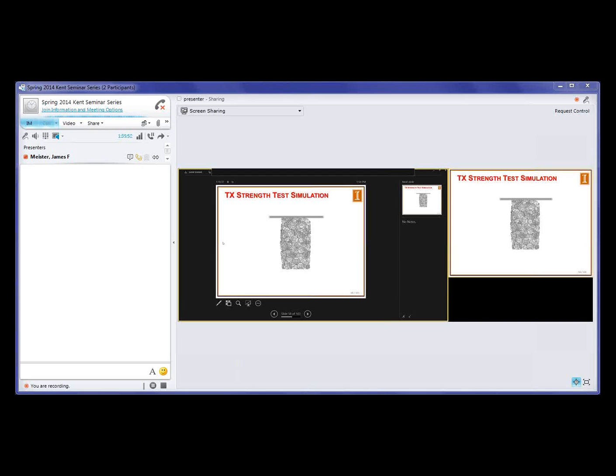The permanent deformation is very similar to this case. So you have a monotonic strength test. You just push the top platen down, right? 10% strain or 5% strain. But in the case of a repeated loading test, it's the same thing. Instead of using a strain-defined target, you use a load-defined one. So you just apply the load on the top of the ballast layer. The force on top of the ballast layer will be distributed to all the particles, and then particles will have lateral movement. So you have the permanent deformation from the top. It's the same mechanism as in the field, right? You push from the top, the particles move laterally. It's kind of like particle flow. Did I answer the question?